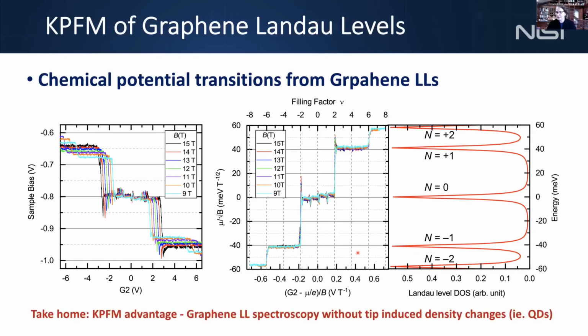And the nice thing about this is that this is done now without any tip gating. Because we're at the 0 force condition, we're at the balance condition where we nulled out the contact potential, we know we don't have any tip-induced density changes. Now, the data I showed you for the quantum dot resonator was done with a tip that had a nicely matched work function with the graphene, so there wasn't any tip-induced quantum density changes. But that's not always the case, and more often than not you'll have an imbalance between the work functions. And in this case, it's actually an extreme case where the work function difference is 0.8 of a volt. You can read that off right from here because the 0 Landau level occurs here at minus 0.8 volts. So if we were to go now to 0 volts and try to measure this n equals 0 Landau level, we would have a huge gating field, and we see nothing more than quantum dot behavior. So it looks like we just created a quantum dot inside our quantum Hall system.